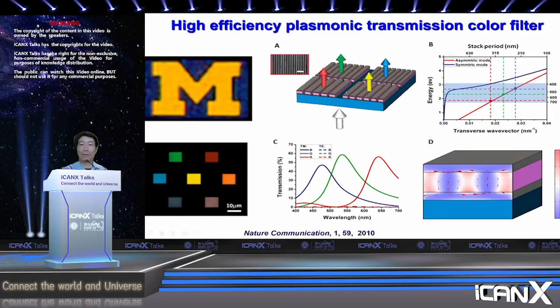But once you cut these nanoscale grooves into this stack, it becomes a nano grating, and then it can actually transmit any desired color you want, just simply by controlling the pitch of the pattern. So on the lower left, you can see these different color pixels that are coming out from the structure. And they actually give pretty high efficiency, 80%.